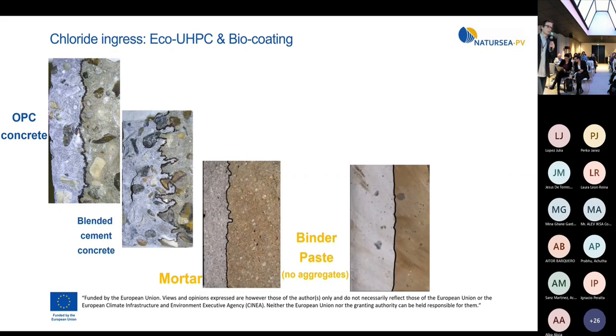For this, we have different tests. One is, for example, a rapid chloride migration test, which is accelerated by voltage, or we could use just natural diffusion tests. When you split and make a cross section, you can see it in the concrete. This student from Delft did it on normal concrete and slag concrete, and they found that because the microstructure of the binder is much denser, the interfacial transition zones between the aggregates and the paste binder are more porous, and you can see how the path actually follows these interfacial transition zones.